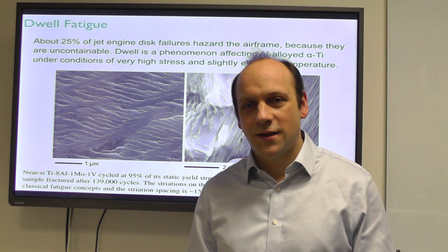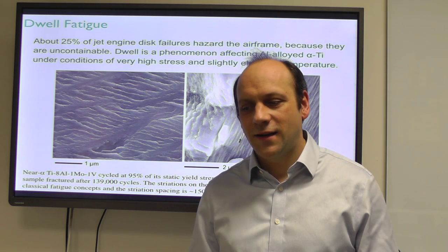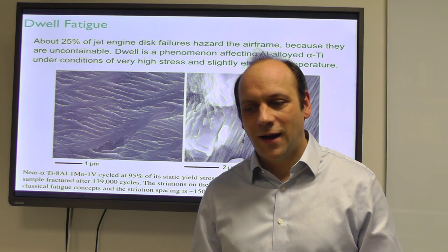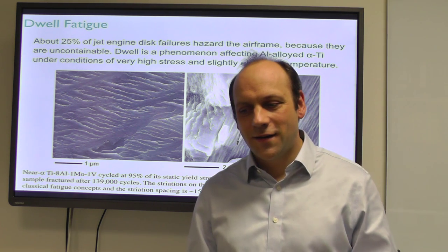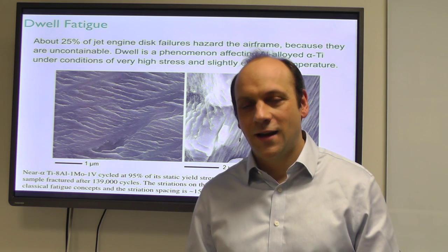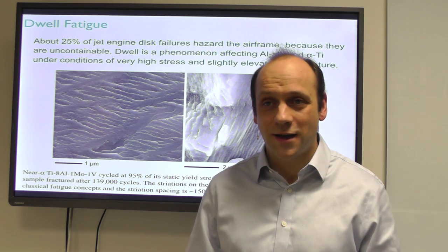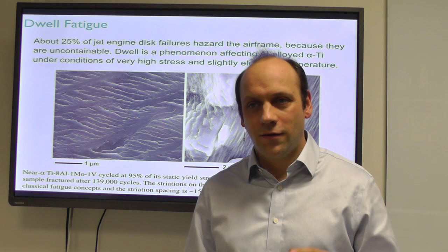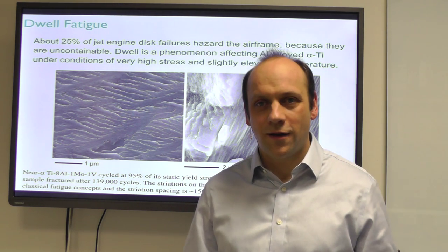Dwell fatigue is a phenomenon affecting aluminium alloyed alpha titanium under conditions of very high stress. And it's called cold dwell fatigue because it tends to happen at low temperatures, up to about 100 degrees C.